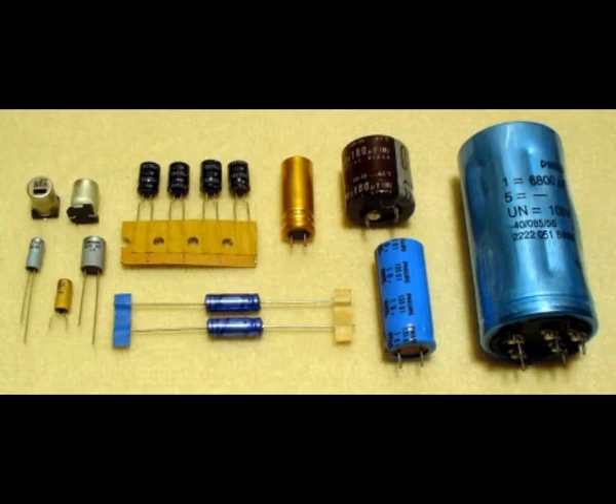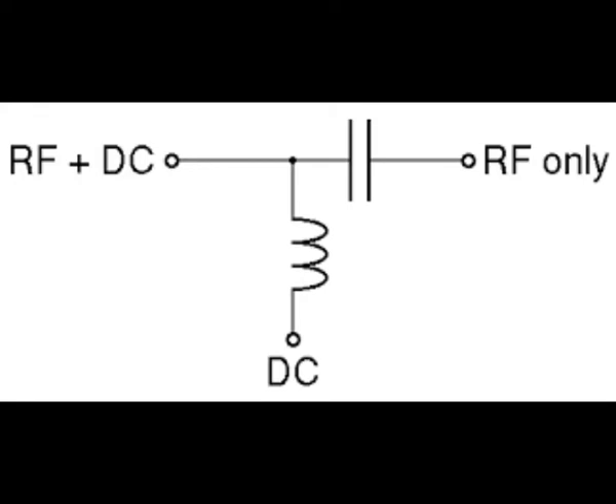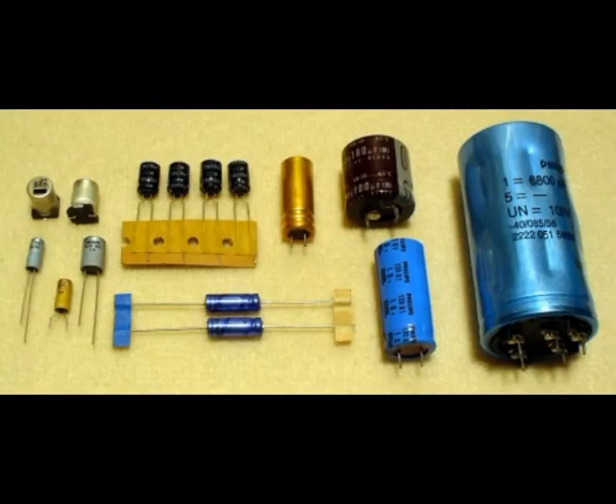In 1983 a further reduction of the ESR was achieved by Sanyo with its OS-CON aluminum electrolytic capacitors. These capacitors use as solid organic conductor the charge transfer salt TTF-TCNQ (tetracyanoquinodimethane), which provided an improvement in conductivity by a factor of 10 with respect to the manganese dioxide electrolyte. The ESR values of TCNQ capacitors were significantly reduced by the discovery of conducting polymers by Alan J. Heeger, Alan MacDiarmid and Hideki Shirakawa. The conductivity of conductive polymers such as polypyrrole or PEDOT is better than that of TCNQ by a factor of 100 to 500, and is close to the conductivity of metals.